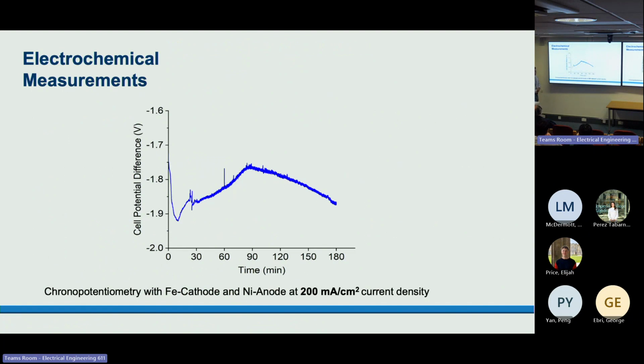We carry out the electrolysis at constant current to keep the initial current density at 200 milliamps per square centimeter. Because as electrolysis carries out, the surface area of the electrodes is getting bigger, so this is the initial current density. But we keep the overall current constant. We measure the change in the voltage. We can see it's ranging from 1.92 volts to around 1.75 volts.